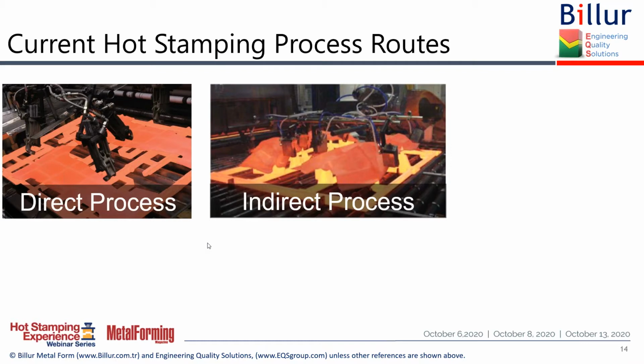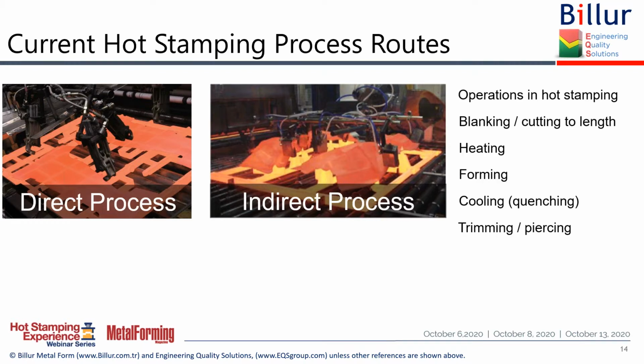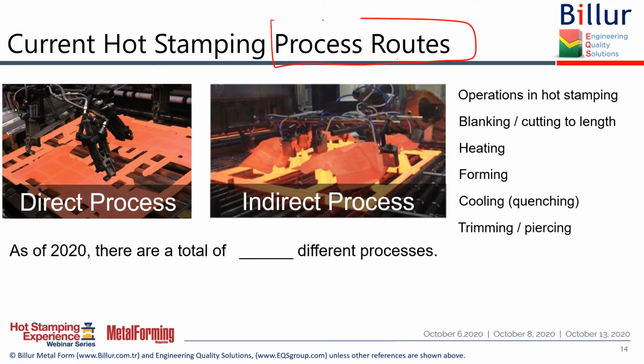So in most resources, you would see there are 2 process routes, direct and indirect. This has been almost correct for a long time. And when we are looking for the process routes, what we should be taking into account is the operations. So we have blanking or cutting to length as one operation, heating as another operation, forming, cooling, quenching, and trimming, piercing. And by changing the route, the operations order, we can get to different processes. As of 2020, there are a total of 10 different processes that I will go through very quickly.